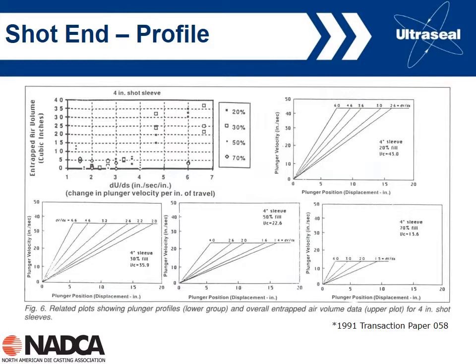And the results are summarized up here in the top left, where we're showing the amount of the entrapped air volume for the different acceleration rates in inches per second per inch, and then also for the different fill ratios. And so what we can see is down here, the amount of entrapped air is low. So basically for an acceleration rate of below 4 inches per second per inch or so, and then above that rate, the amount of entrapped air becomes significantly higher. So again, this is giving you additional information in terms of the optimum slow shot velocity to be used in cold chamber die casting.